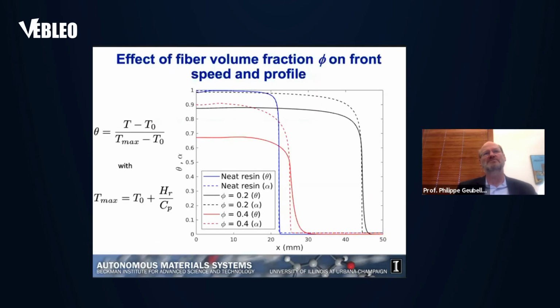And indeed, if you actually plot here the solution that you obtain for the neat resin, so in the absence of any fiber, 20% fibers and 40% fibers, we can see 2 things. First, as you increase the fiber volume fraction, the temperature tends to decrease. And it's expected, once again, because the fibers take some of the heat generated by the exothermic reaction. But also what we observe is that the front, which was the blue one, that was the neat resin case, seems to propagate faster when we go to 20% fiber volume fraction, and then a bit slower afterwards when we go to 40%.